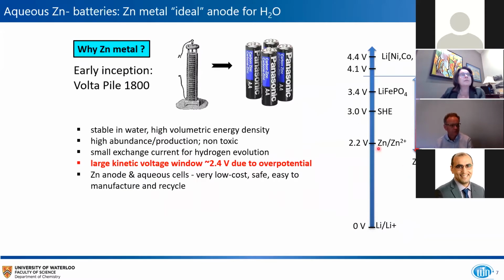So I'll just mention a few things about our zinc ion batteries. And one might ask, why zinc metal? Of course, this started off with the Volta pile in 1800. And the point is that zinc is stable in water. It actually has high volumetric energy density. I feel like I'm taking coals to Newcastle because I'm sure you know all about zinc batteries at the University of Sydney, but anyway. For those who may not be familiar with this, zinc is obviously high abundance, it's non-toxic, and especially it has a small exchange current for hydrogen evolution and a large kinetic window due to this overpotential for hydrogen evolution.